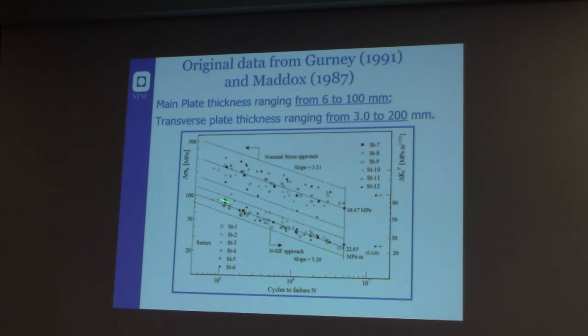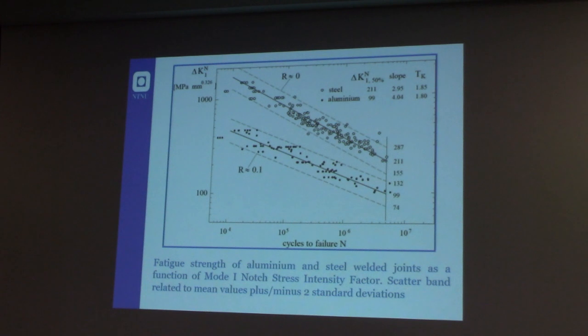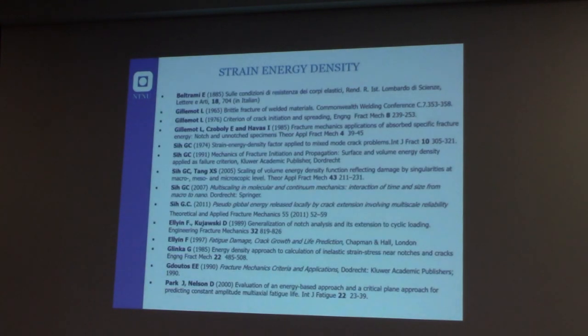If you summarize the results considering the notch stress intensity factor at the weld toe, you have a very, very narrow scatter band. This means that the notch stress intensity factor is a very powerful tool for designing a welded component if the failure is occurring at the weld toe. And they also extended this to aluminum components later. So it's not only for steel but also for aluminum welded joints.